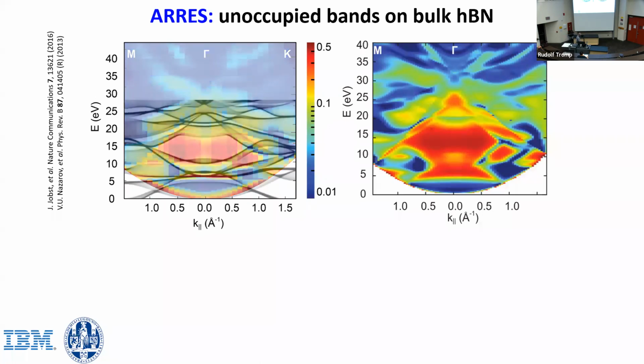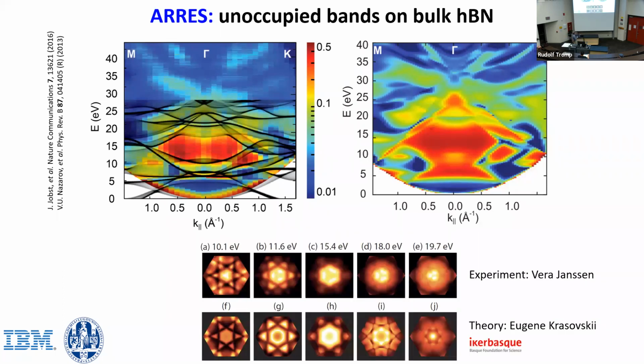And if you just plot the band structure on top of that, you indeed see a large band gap in the band structure here. You see these side bands appear and everything. So this simple reflectivity experiment actually shows you the band structure of the material rather directly. And we can actually do that in 3 dimensions. So here are slices, this is just in one direction, but we can do kx, ky, and get the whole 3-dimensional figure, right?